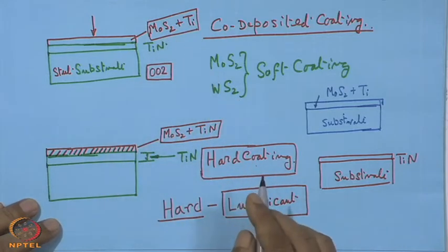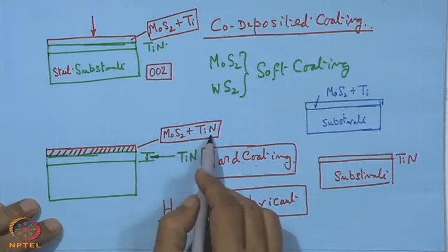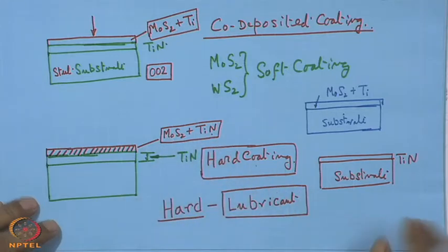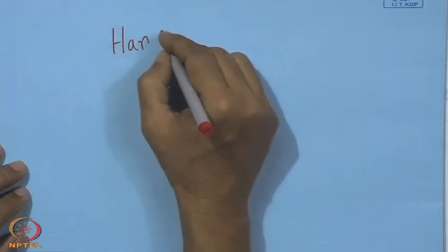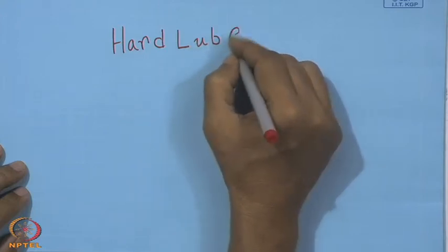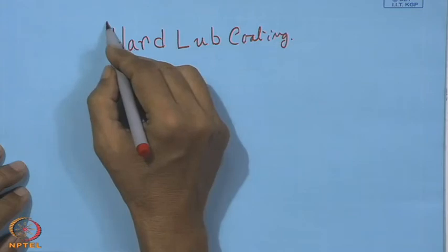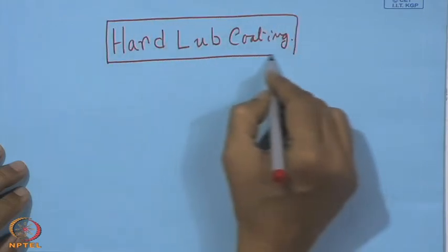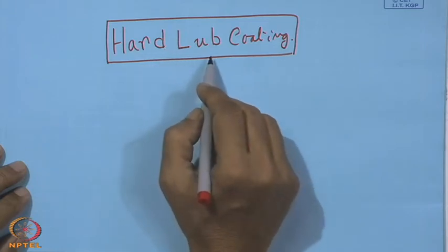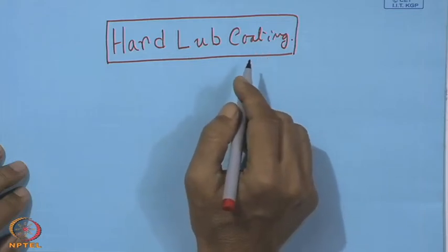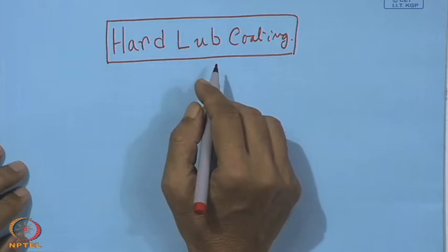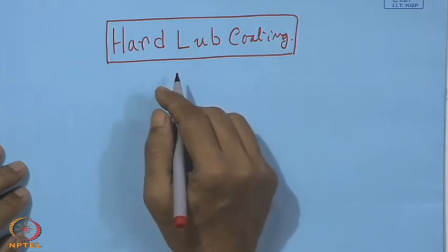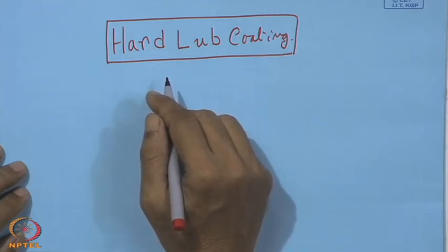And that is the idea behind here, to have this blending of hard coating and lubricious coating, and that is why one can also call it a hard-lube coating. So, it is actually a hard coating and the self-lubricating coating. So, this coating can be used for all sort of applications, like machining as a cutting tool, in metal forming, die punches and similar areas, where this can find extensive use.